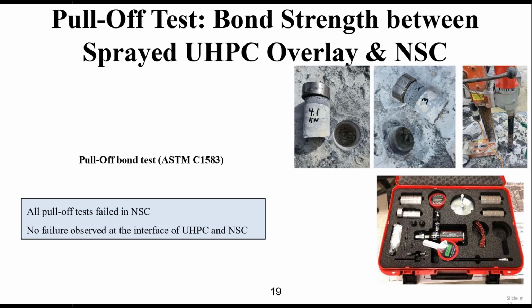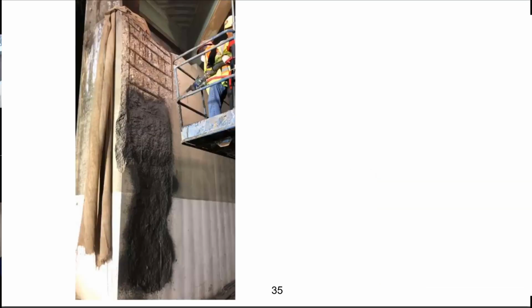But you go in a very thin layer, and then you have to have some time gap before applying the second layer. If you apply it too soon, the second layer may slip with respect to the previous layer. But if you give the first layer time to dry up a little bit, you can apply the second layer, third layer, fourth layer, and so on. So you can go up to 1 inch if you want to.